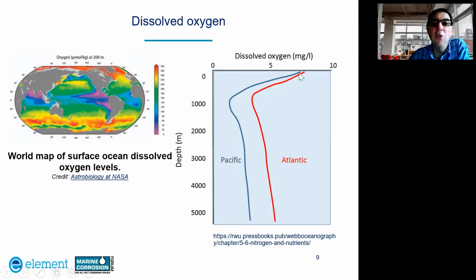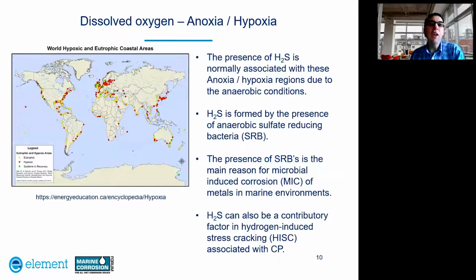As you go down, you get a steep decrease in the dissolved oxygen, and then it's fairly stable as you go deeper. And this sketch illustrates the difference between the Pacific Ocean and the Atlantic Ocean in the actual dissolved oxygen content. If we're looking at oxygen, there are certain areas around the world where there's a depletion in oxygen, which is called anoxia or hypoxia. In these regions, the presence of hydrogen sulfide is normally associated with these anoxia or hypoxia regions due to the anaerobic conditions.